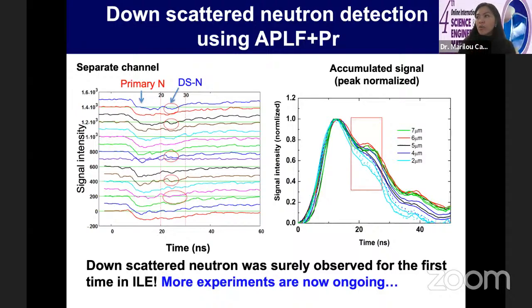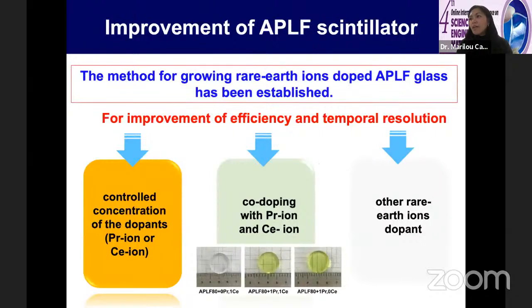So using that scintillator array, we were able to successfully detect the scattered neutrons during nuclear fusion. These are individual measurements from individual arrays showing the primary neutrons and then the weaker downscattered neutrons. But if we integrate the signals, we can come up with a more discernible curve showing the primary neutrons and clearly distinguishing the scattered neutrons from the primary neutrons. But more experiments are now ongoing, and despite the success of praseodymium doped APLF, still more work has to be done.